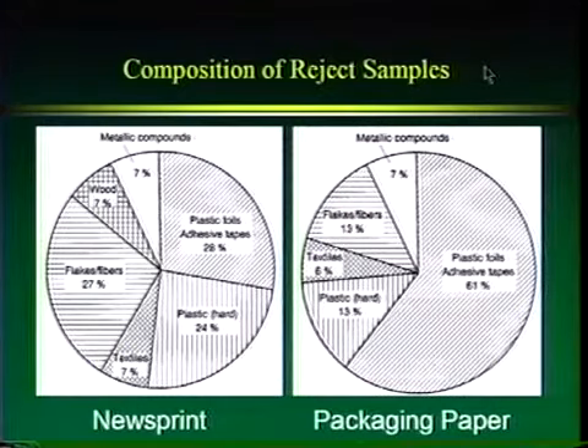Okay, so if we look at some of the composition of reject samples, and recall rejects are the coarser, larger material that comes out near the pulper. What you'll see is we've got a lot of plastics, almost 50% plastics in our rejects. We've got some flakes and fibers of unpulped material, maybe wet strength. We've got wood, metal, and textiles. And that's for a newsprint de-inking plant. So this plant is probably bringing in newsprint and magazines.